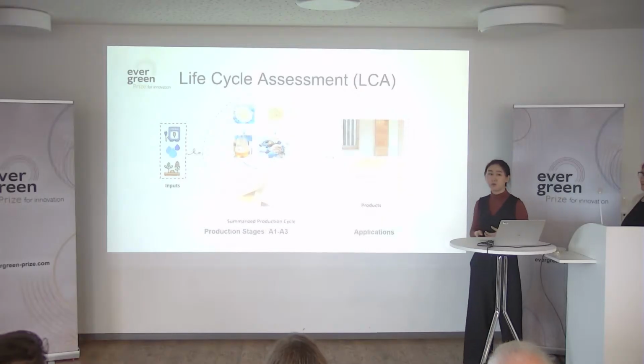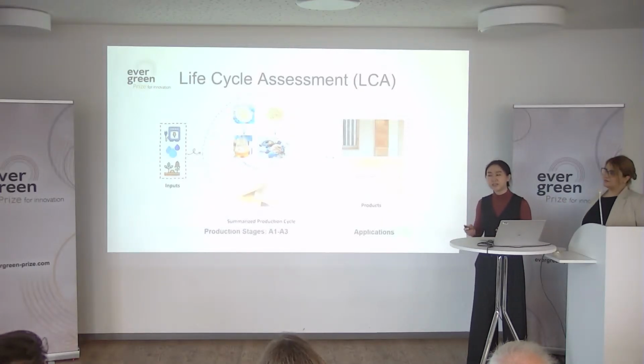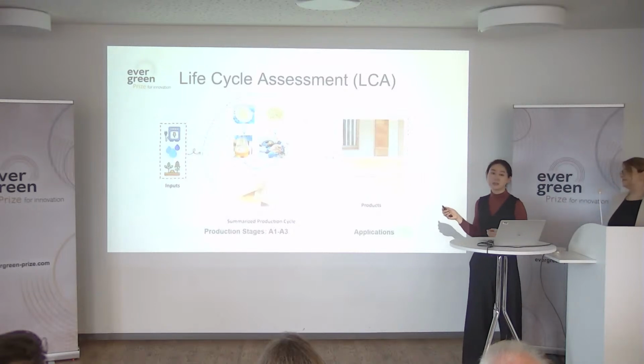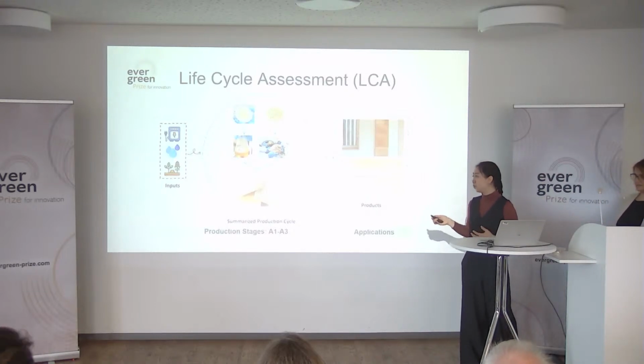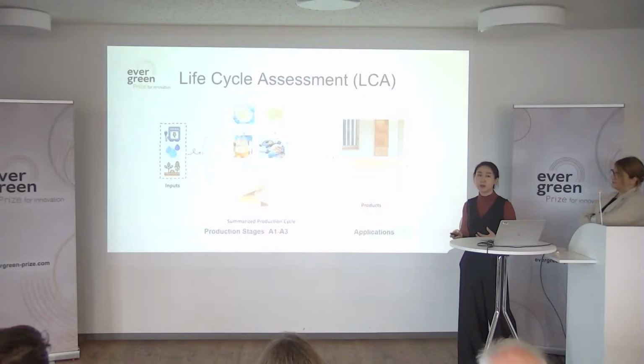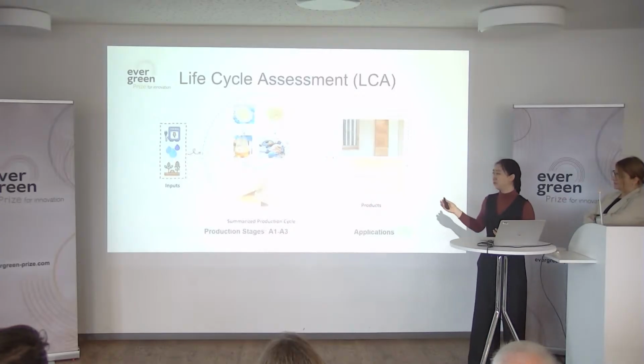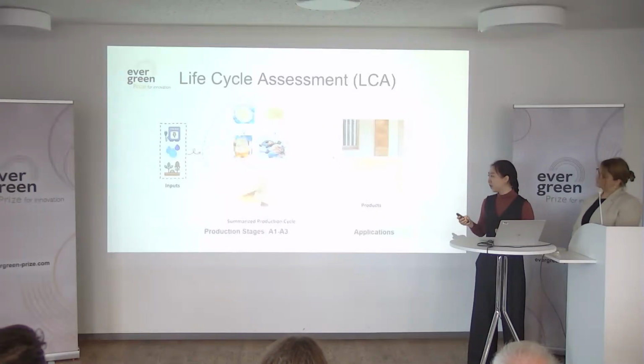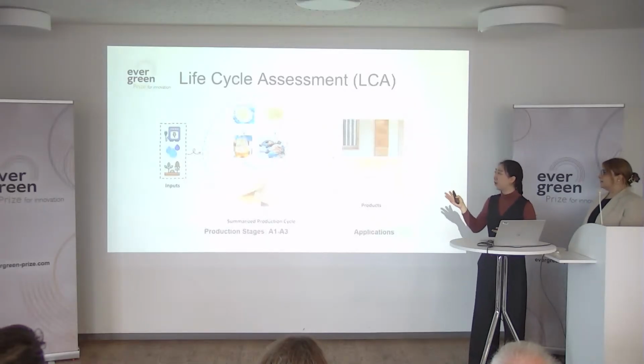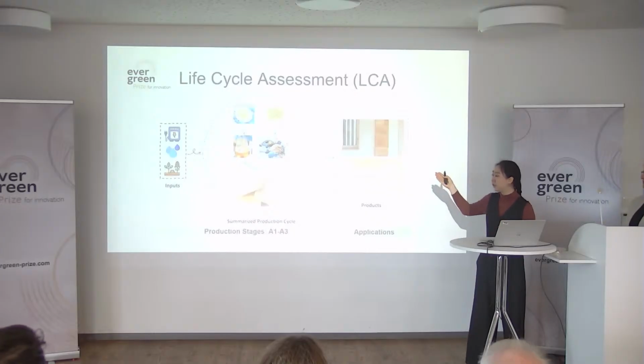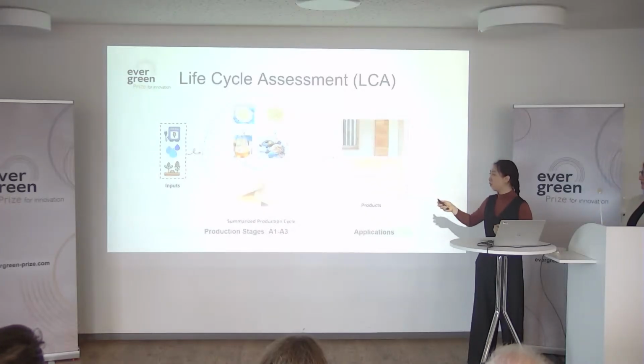So when we talk about green materials, of course we have to actually think critically whether is it green or is it really actually good for the environment. So what we did was that we conducted some life cycle assessment on our material. What we did was that we modeled the production process of our mycelium-bound composites into 3 different stages. And for each stage, we will model and calculate the inputs and the products from each stage. The three different stages can be summarized as follows: the growth and culture stage, the incubation and inoculation, and then the processing stage for the final products.